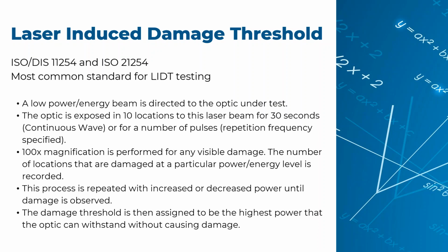After this is done, and this is unique to laser-induced damage threshold testing, 100x magnification is performed to see if there's any visible damage. And then the number of locations that are damaged at a specific power or energy level is recorded. After this test is done, you can repeat it, and then the damage threshold is assigned to the highest power that the optic can withstand without causing damage. So that's a really quick generic description of laser-induced damage threshold.